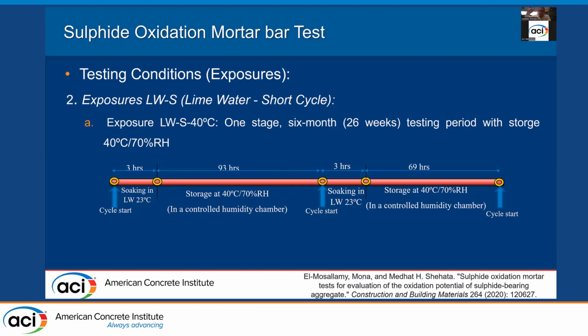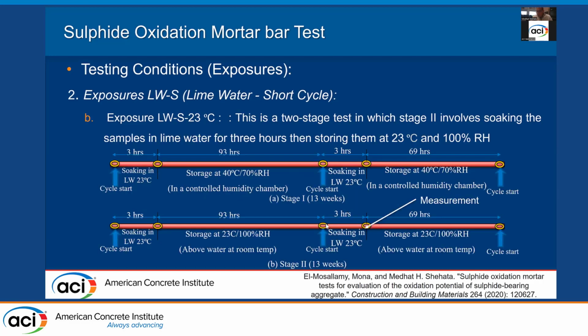So you're actually testing the material at a range of relative humidity that starts from 100 and can go down to close to 70, but not lower than 70. At that relative humidity, I assume that you will have a little bit of oxygen penetration to get oxidation. I assume that you might get a little bit of ettringite or sulfate attack because of the high humidity and because of the soaking as well. So that's the same testing as phase 2.